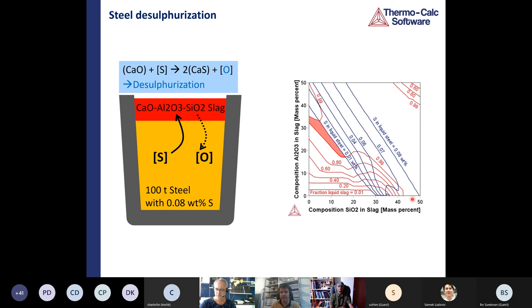What I calculate here is I vary the slag composition from pure calcium oxide here, increasing the silicon content on the x-axis, increasing the aluminium content on the y-axis, and have contour lines. The red contour lines tell me if that slag for this composition is actually liquid or not. Down here, if it's pure lime, it's fully solid. This is useless because it'll just float as an island on top of my steel and will not react with the steel for kinetic reasons. Only if I'm in this region here will it be fully liquid. So that's the first condition that the slag has to have.